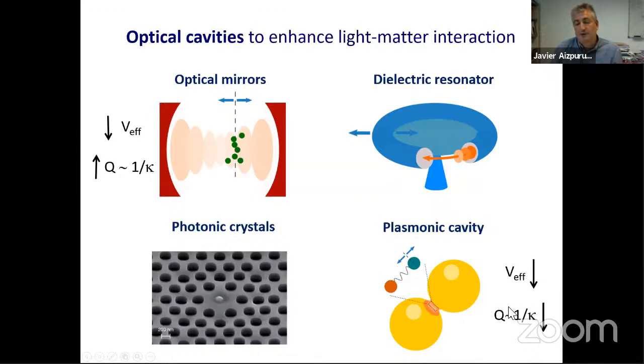But the drawback and the price to pay is that because the handling of the photons is done via electrons and electron dynamics of the cavity, and electrons are very lossy, they have lots of ohmic losses associated to them. And then the losses are very large. In other words, the quality factor is very small. Sometimes a good metallic cavity has a quality factor of 10 or 20, in the best case scenario. After 20 optical cycles or 10 optical cycles, the photon is gone. That's the trade-off. So you gain in condensing, trapping the energy in very tiny volumes, interacting more efficiently in that volume, but you lose the photon very quickly, okay?